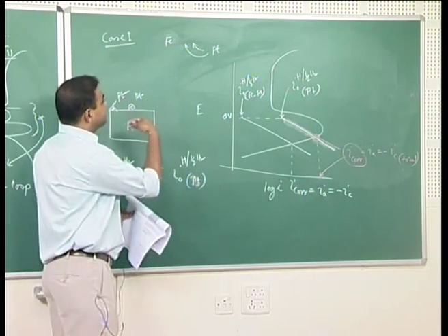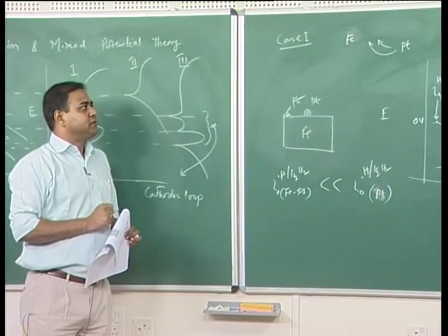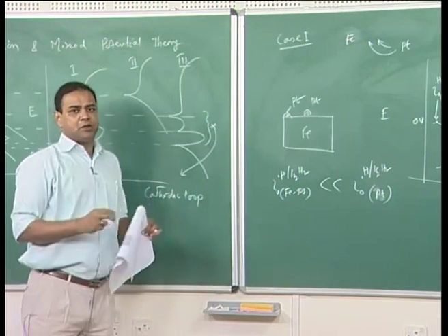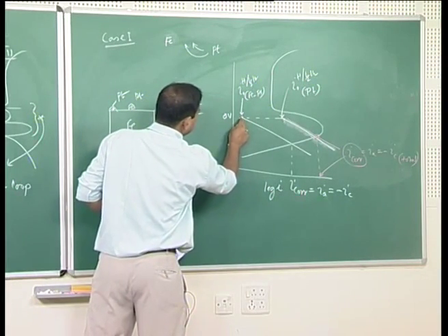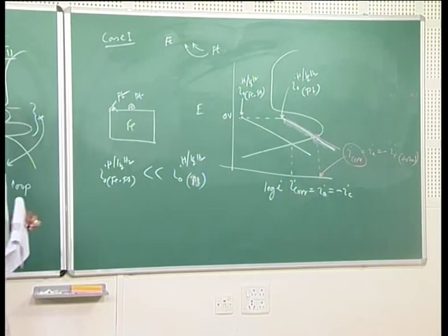So, here though you are getting a positive effect because of an addition of noble metal, that is platinum in titanium, in case of iron it gives the negative effect, because of the position of this point with respect to the anodic polarization plot for iron in the air free acid.